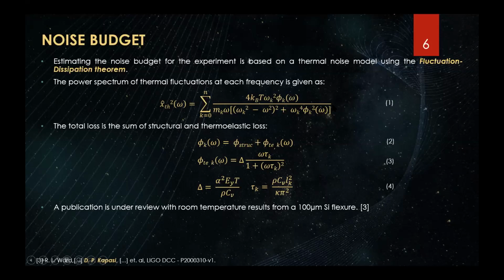And phi_total is your total loss, which in our case, our cantilever is mainly dominated by structural and thermoelastic. So this is your thermoelastic loss, which depends on a characteristic time, and it depends on material properties like your coefficient of thermal expansion over here, alpha, and also on the temperature, which plays an important role when you start cooling things down. Also, we have a publication under review, which has room temperature results from a 100 micron silicon flexure that was done earlier.